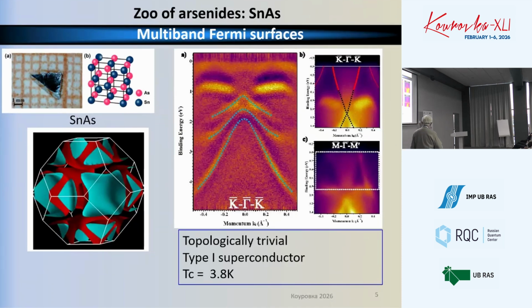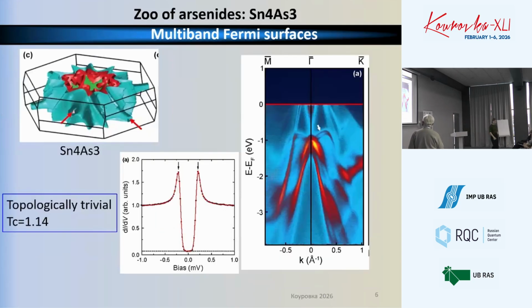Just a little bit more detailed analysis shows that it is a type 1 superconductor. To conclude this, you have to obtain the density and all the parameters of the Fermi surface. Almost with no doubt you conclude that it's a type 1 superconductor. Nothing specific, no puzzles. The next is tin 4 arsenic 3, and it is also semi-metallic. It has a nicely pronounced gap that can be revealed by scanning tunneling microscopy. Critical temperature is 1.14, and also this is a type 1 superconductor. No puzzles, just for the beginning that these are pure semi-metals.